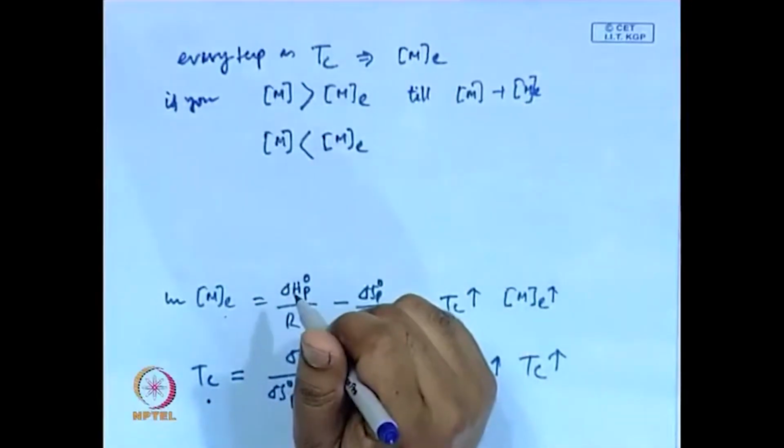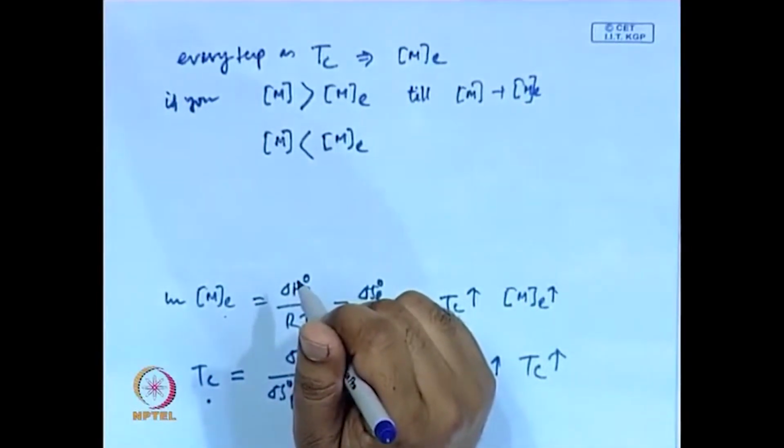Rather, if polymer chains can be broken some place and you get a radical or some active center, the polymers will depropagate, unzip to form monomers, so that the free monomer concentration goes up and gives you the equilibrium monomer concentration.